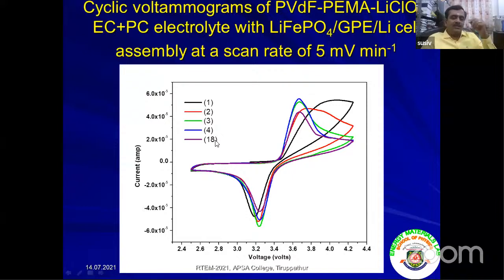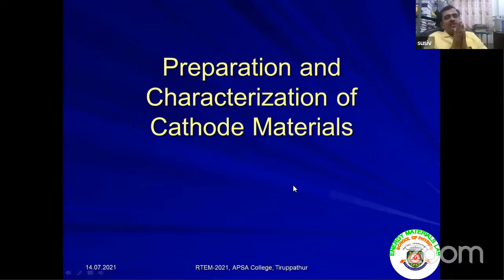Using this, we are seeing the cyclic voltammetry of the prepared gel polymer electrolyte film, using PVDF and PEMA, LiClO4 and EC PC, with LiFePO4 and lithium, that is nothing but a half cell. If you use an intercalated material anode here also, it is called a lithium ion cell, that is a full cell. It is performed at a scan rate of 5 millivolt per minute, and see the oxidation and reduction of LiFePO4 happening at 3.7 and 3.2 volt.